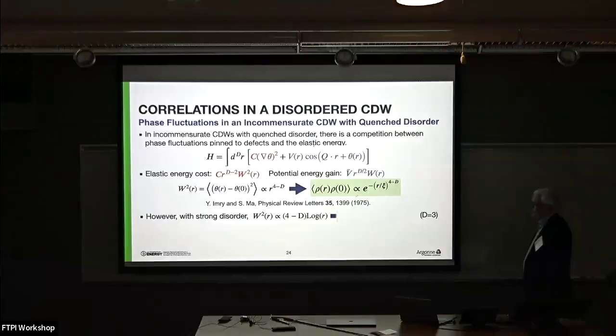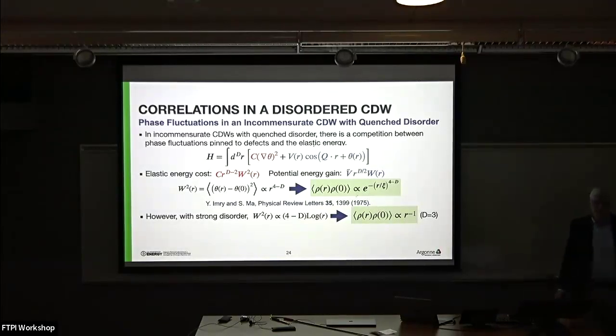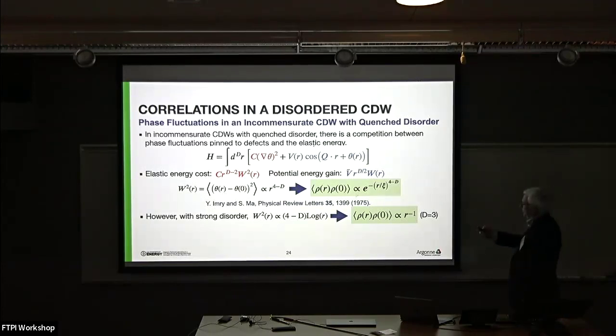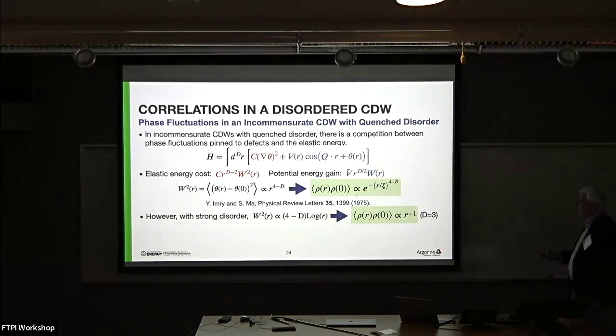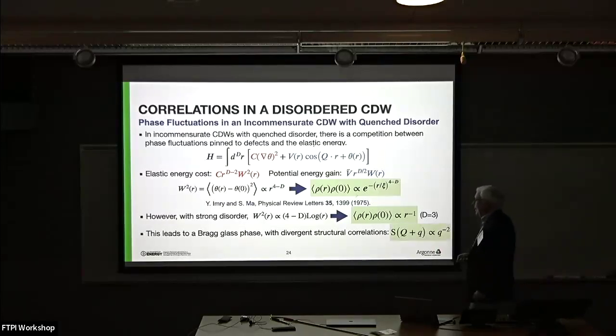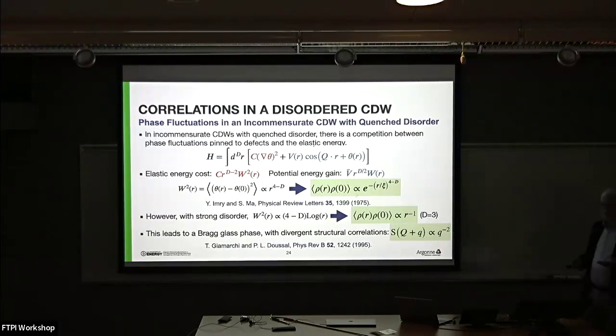But it was realized in the 90s or so that actually the phase is bounded in these materials. So there can be solutions to this where you're not, this assumed a linearization of that disorder potential, V(r) times phi. If you didn't assume that, then you can have circumstances in which the phase fluctuations decay logarithmically rather than as a power law, and the result is a density function that decays as 1 over r, and that actually leads to divergent structural correlations. These divergences are happening at the CDW wave vector, but it's not a Bragg peak, okay? And it's incredibly difficult to tell the difference between this and a Bragg peak because basically they're both essentially resolution limited peaks, okay?